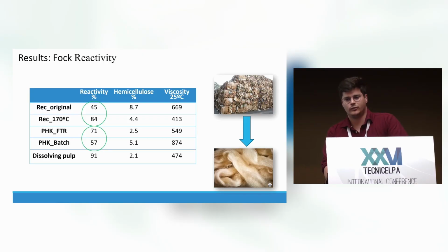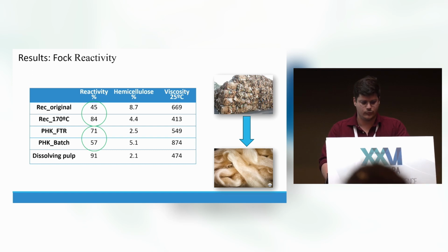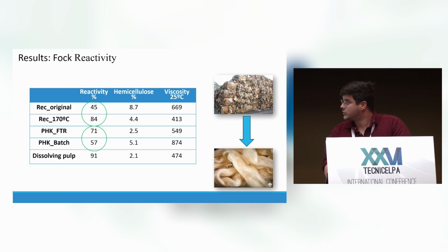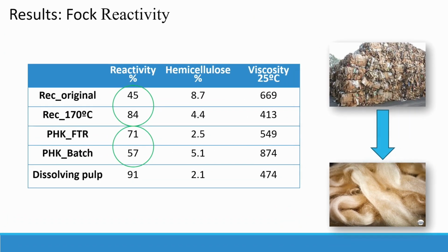Regarding reactivity, we have interesting results, particularly when studying the recycled pulp. We can see that we almost doubled the Fock reactivity of this pulp when employing the two chemical treatments. One of the interesting points is that we cannot remove a lot of hemicellulose in this process due to the characteristics of this pulp. However, due to reduced viscosity, we have this increase in reactivity.